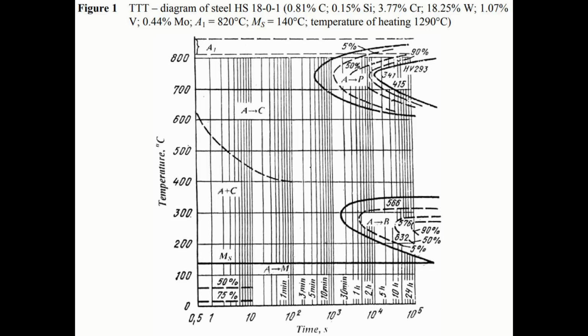And the reason for this is that high alloy steels are actually designed for about 0.4 to 0.6% carbon in solution. Just like how I discussed 52100 has usually around 0.6% carbon in solution with the extra chromium that's in there. High alloy tool steels have lots of alloying elements, and we typically austenitize them at a temperature where we get in that correct, I'll call it, carbon in solution range, where we have enough carbon in solution for the high hardness that we want, but not so high that we start to drop our toughness with plate martensite. Also, high alloy tool steels can have issues with retained austenite if they are austenitized too high and too much carbon in solution with the extra alloy.